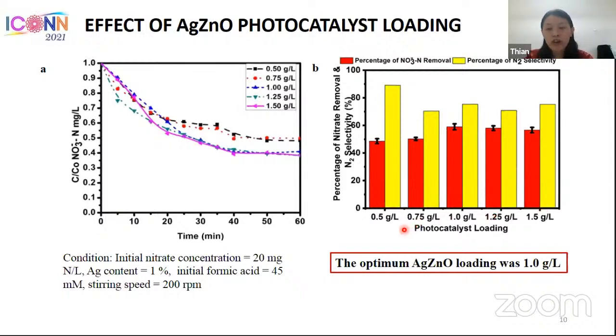So again, similarly, if we increase the photocatalyst loading from 0.5 to 1 gram per liter, we can observe an increment in percentage of nitrate removal, but beyond 1 gram per liter, it doesn't give us any significant changes. So we can say that 1 gram per liter is the optimal photocatalyst loading. It can be rationalized that if we keep on increasing silver zinc oxide, we also increase the photocatalytic sites. So that is why we can observe the increment here.